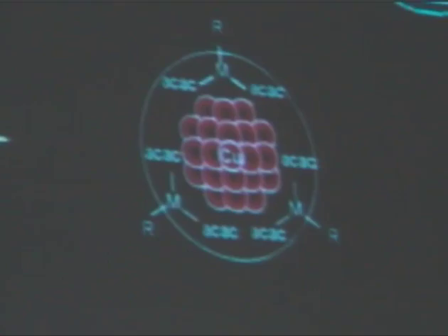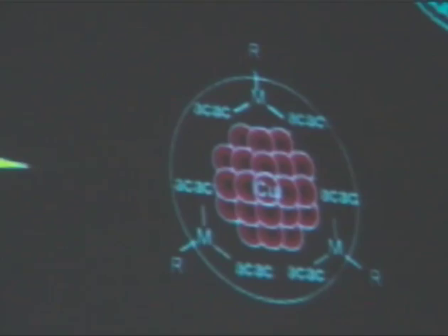And what we then get is essentially a layer which is an alkyl acetonato aluminum or zinc layer over the copper nanoparticles. Conditions of the reduction, for instance the chain length of the alkyl, determine to some extent the size and size distribution of the particles. This is what you get with aluminum octyl. The particles are on average about 4 nanometers in size, the copper particles. Aluminum butyl, they are somewhat bigger, going to 6, 7, 8 nanometers in size. The zinc butyl ones are again in the same size range as the aluminum butyl stabilized ones.